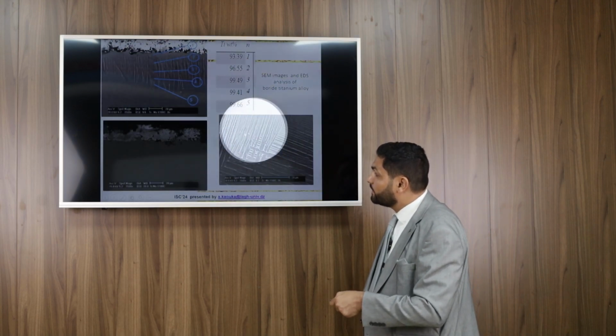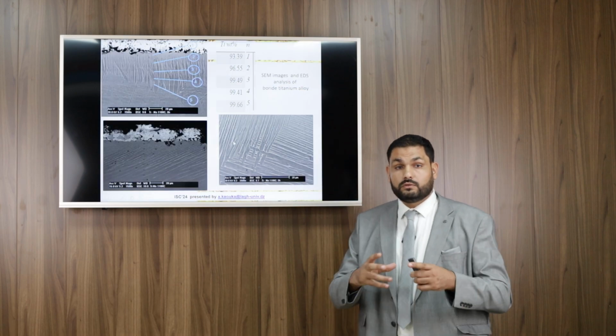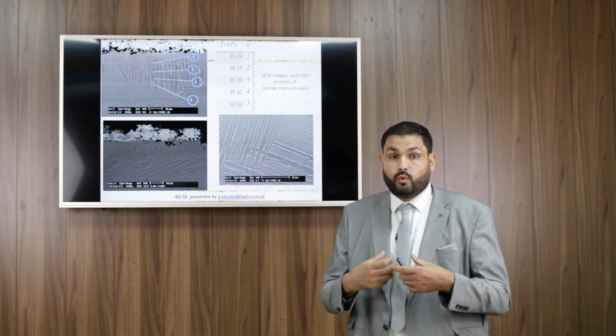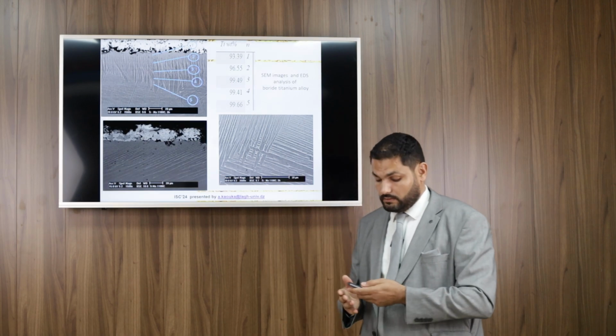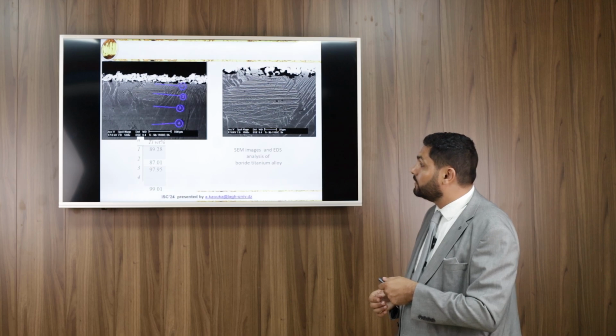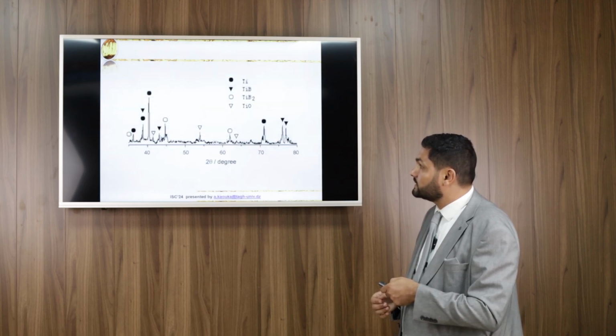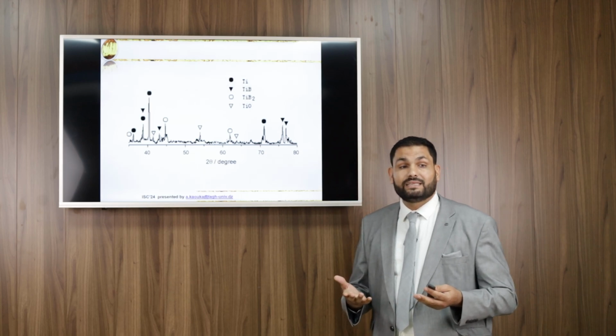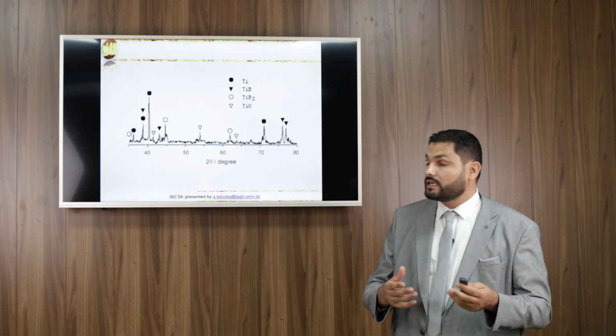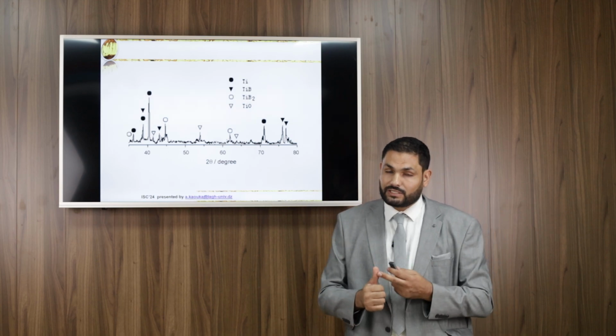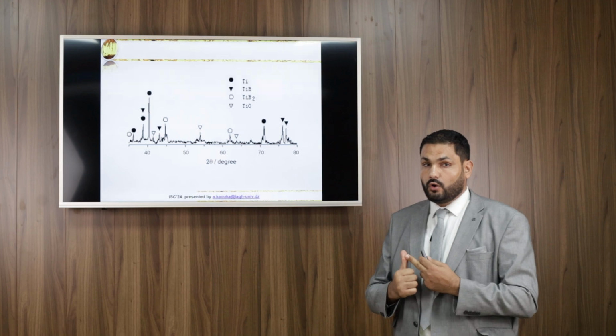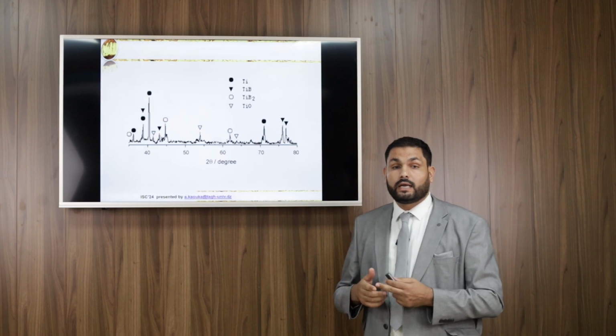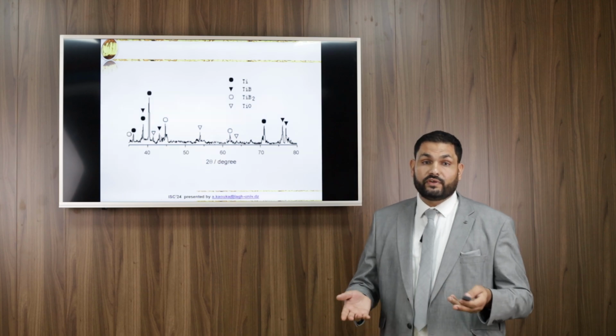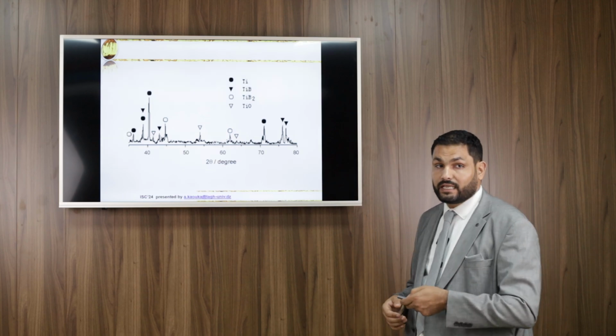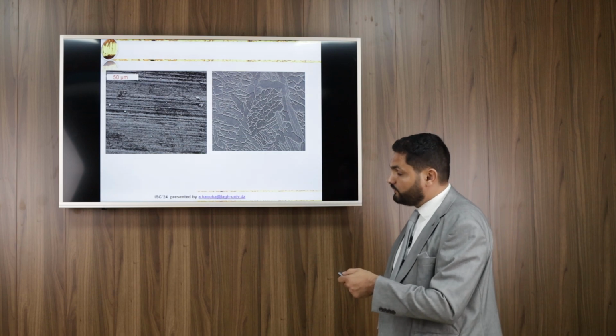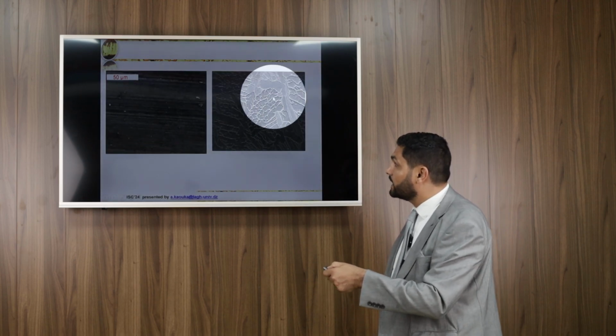We see a laminar structure, a laminar shape, as you see here. As you know, the structure of titanium alloy is usually equiaxed, and here it is laminar, so the form of boride formed on the surface changed with the treatment. This is SEM. With X-ray diffraction, we confirmed that we have titanium alloy, titanium oxide, titanium boride and titanium diboride. We confirmed these phases by X-ray diffraction.